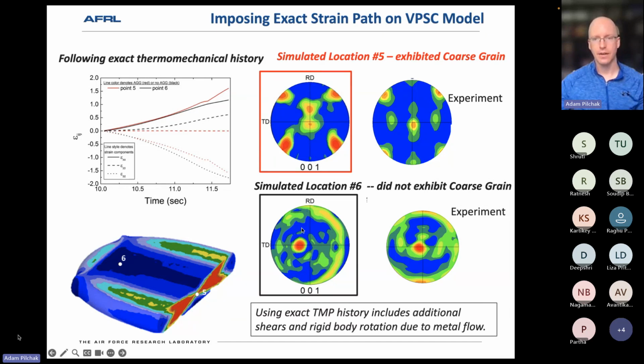So on the left-hand side, we've got for those 2 locations the simulated textures, and then on the right-hand side are the experimental textures. For anyone who's done crystal plasticity simulations, this is actually pretty good. I was pretty pleased by this. We've got a couple spurious intensities over there, but overall we've captured a lot of the main texture components at point 5. But the one I was most happy about was point 6 here, where we even got the slight misalignment between 001 and the compression axis, and the fact that it had simulated this ring around the pole figure, indicating a more uniform distribution of orientations on that 001 partial fiber, was pretty exciting.